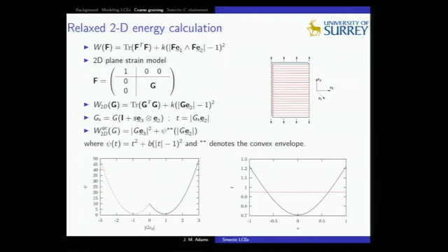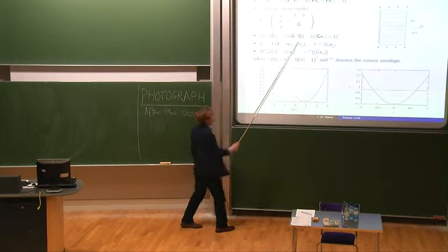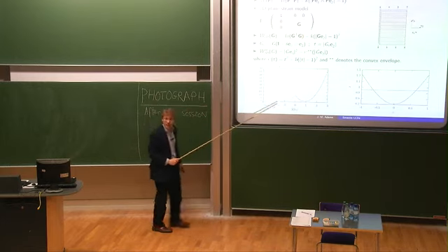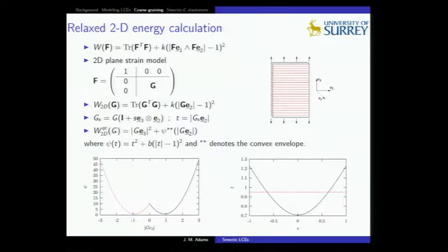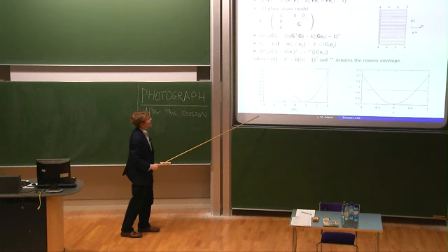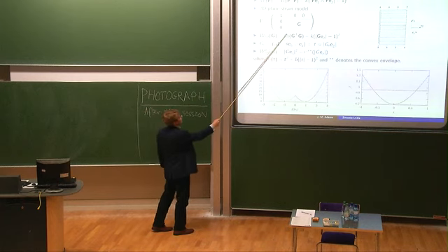Then the second part of the energy simplifies because F E1 just remains E1, and then you've got E1 cross whatever F does to E2, and you can just write that as norm G E2. And so this is the simplified two-dimensional version of our Smectic A energy. Then if you substitute in a deformation G with this additional part, some sort of shear, this gives you a set of rank 1 connected deformations with some amplitude S. You can substitute this into your energy.